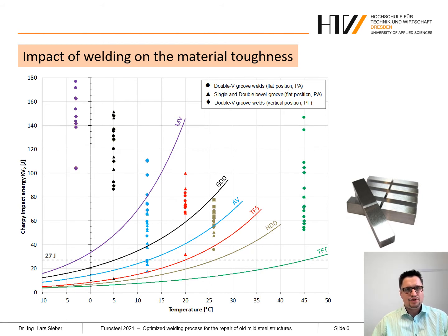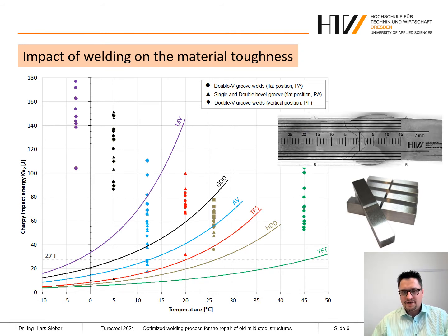Subsequently, at this temperature for each material, notch impact specimens with a notch in the heat affected zone, as you can see here, were fabricated and also analyzed. In this diagram, you see the results of the Charpy impact tests on specimens with different weld grooves and also welding positions. As expected, in most cases, the toughness was significantly higher than in the base material.